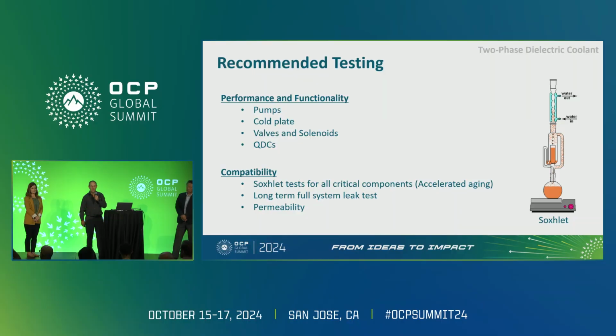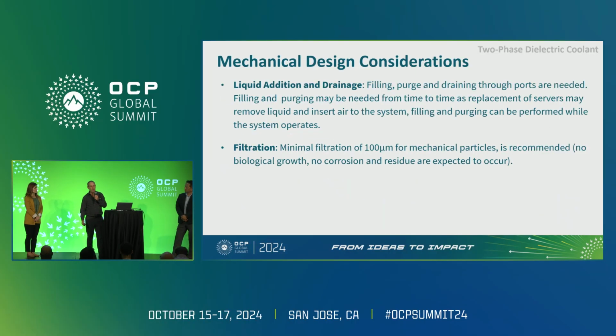One of the tests is a Soxhlet test, which is what we call accelerated aging. 72 hours in a Soxhlet test is equivalent to 3 or 4 months of work in a system. But at the same time, we recommend a long-term full system leak test to see that the system is completely sealed. And we recommend testing permeability so you do not lose liquid from the system through any of the sealings or the tubing.